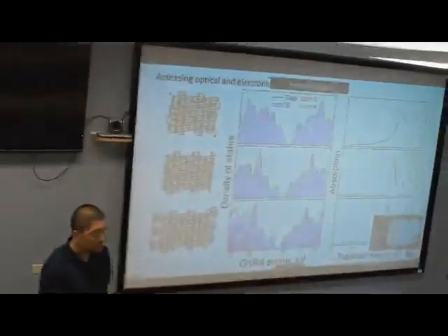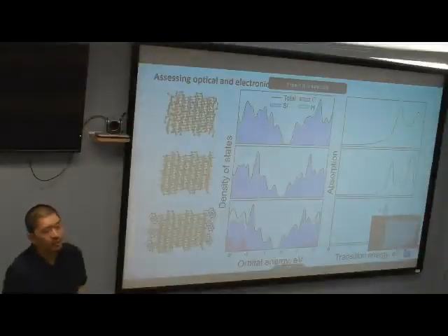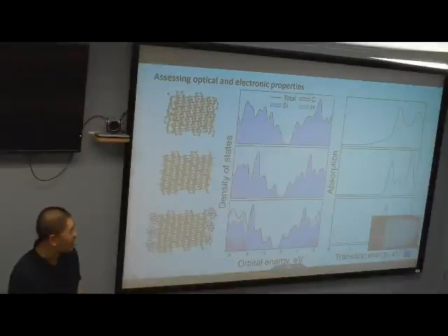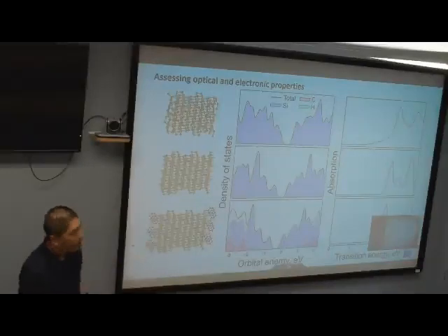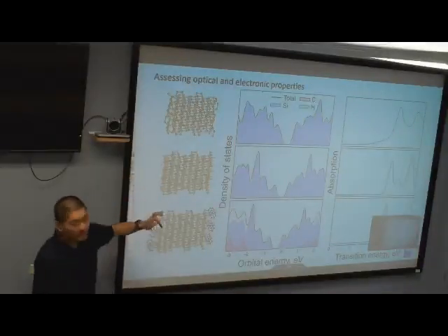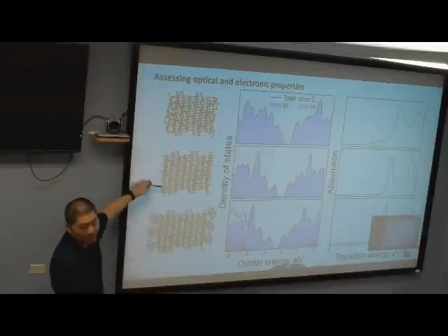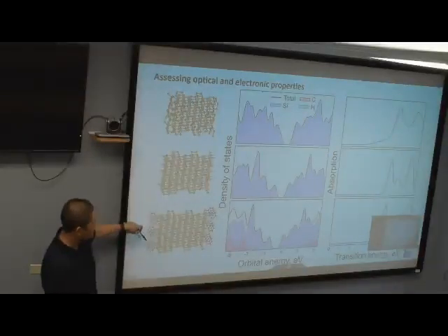So, based on our molecular dynamics calculations, we found that by using diazonium salt, we can actually cap the silicon surface with phenol groups. And then at this stage, we want to compare electronic properties of different slabs. This is a bare slab without any ligands. This is a hydrogen passivated slab. This is a phenol passivated slab.